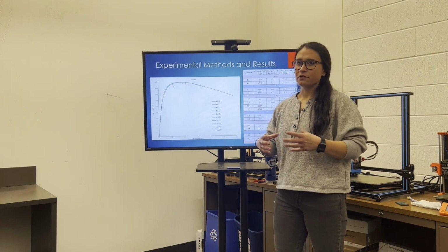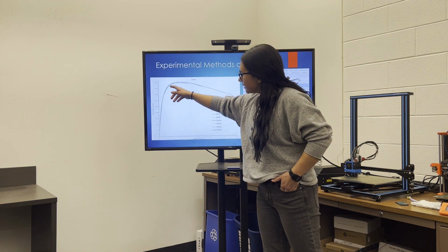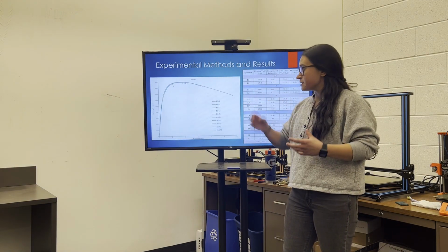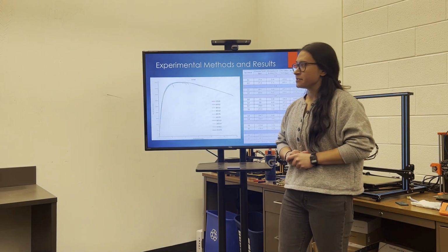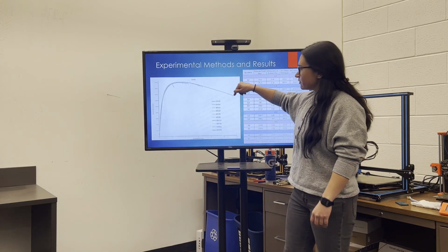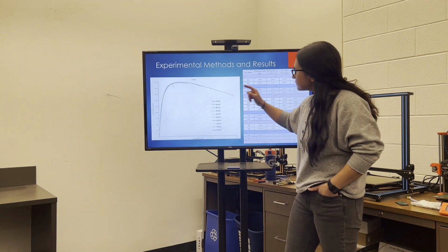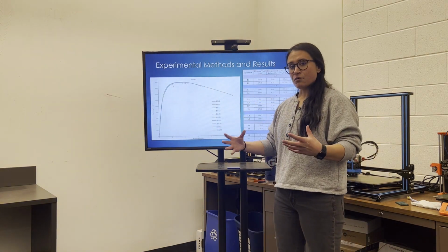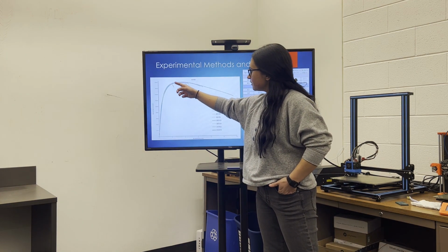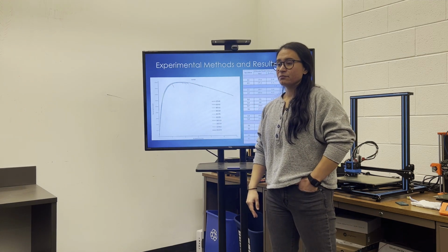The 2.5, which is closest to the center of the billet, tracks to about 2% elongation here versus the most exterior of that 15-inch diameter billet was the 13.9 specimen, which we see similar yield trends, but much more elongation, about 6 times more. Working from the center outwards of the billet, we do kind of see similar trends of elongation, but there are some outliers that failed pretty unpredictably.